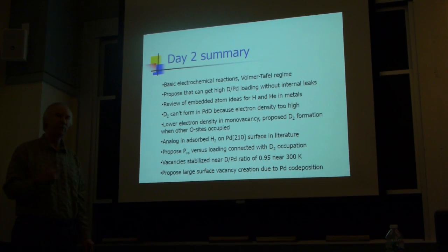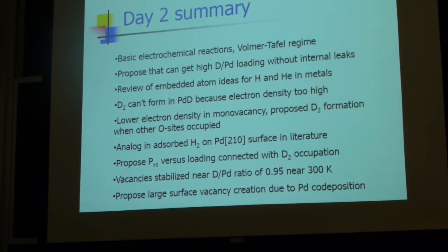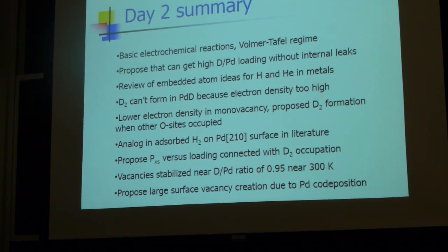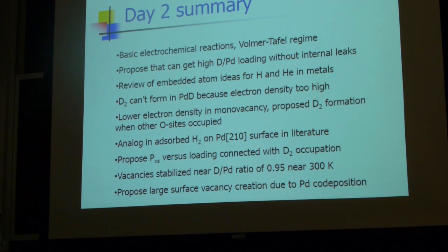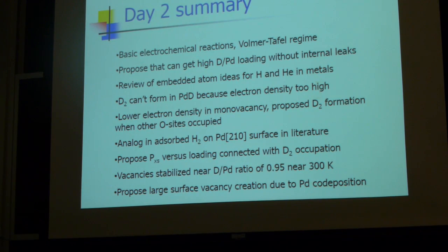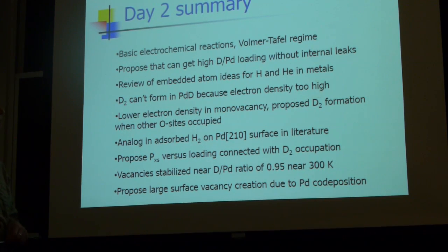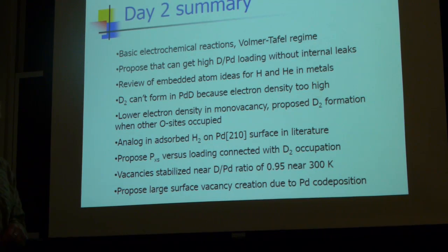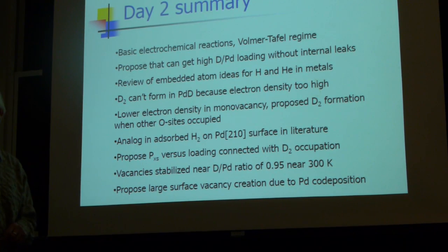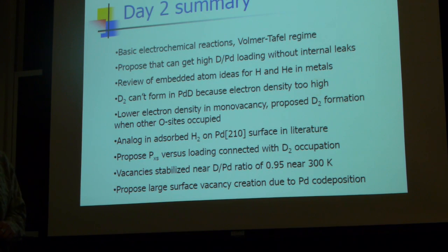D2 is not going to form in bulk palladium deuteride because the electron density is too high basically everywhere. And having the electron density high causes occupation of anti-bonding states that pushes the deuterons apart. On the other hand, if we introduce a vacancy, we can lower the electron density. And from my perspective, that's kind of the key to what the Fleischmann-Pons experiment, as an exercise in physical chemistry,